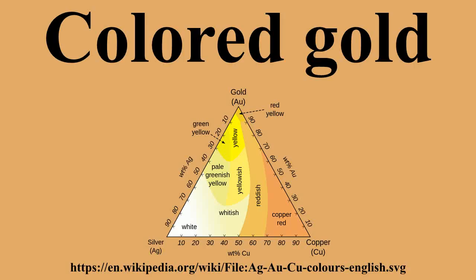Spangold. Some gold-copper-aluminium alloys form a fine surface texture at heat treatment, yielding an interesting spangling effect. At cooling, they undergo a quasi-martensitic transformation from body-centered cubic to body-centered tetragonal phase. The transformation does not depend on the cooling rate. A polished object is heated in hot oil to 150 to 200 degrees Celsius for 10 minutes, then cooled below 20 degrees Celsius, forming a sparkly surface covered with tiny facets.